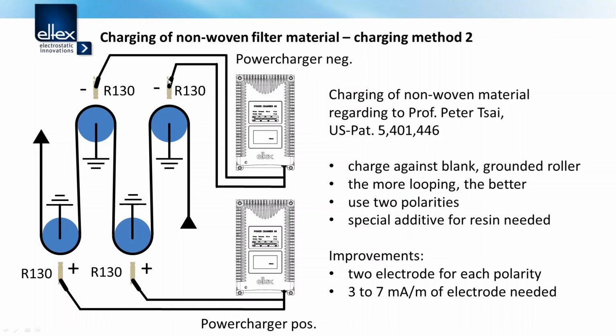We use 2 polarity, negative and positive, and a special additive for the resin is needed to get the charge to stay on the material. The improvements we have done, we need 2 electrodes for each polarity, negative and positive, and we need a milliampere per meter of electrode of about 3 to 7.